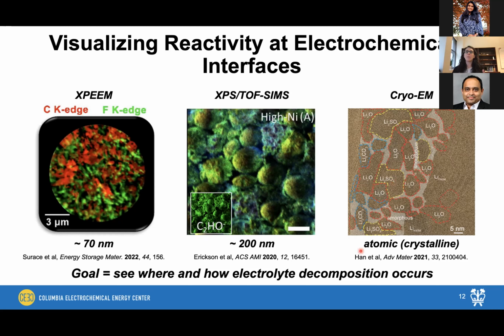One thing about all of these individual techniques is that they all have to be performed under ultra high vacuum conditions. And what this means is that in order to collect this data, we have to wash the sample so that there's no charging under ultra high vacuum conditions. And whenever we wash the samples, this inherently means that we might be disrupting this very delicate interface layer that's built up on the battery during electrochemical cycling.